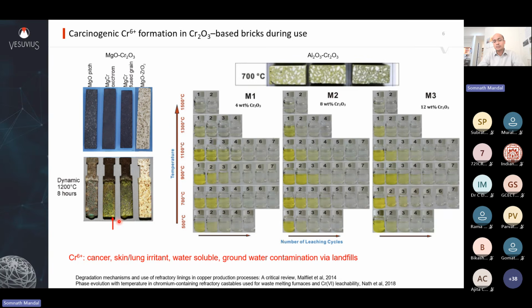And these are very dangerous because they are easily water soluble, and if it is landfilled then it slowly leaches into groundwater and causes long term water pollution. And you see that high temperature is not where this is active. It is the intermediate temperatures from 500 to 1300 degrees Celsius, especially in the 900 to 1100 degrees C, and at 700 degrees C. In this range it is very, very active. And you can see even with this 4%, this fluorescent yellow is the trademark of this hexavalent dangerous toxic chromium variety. And as you go higher up in chrome content, you end up with more and more. And this is only caused by calcia, or soda, and some of these alkali or alkaline earth metals converting it to hexavalent chromium.